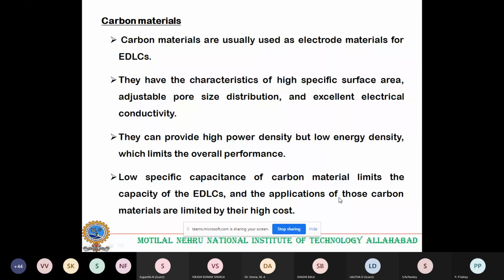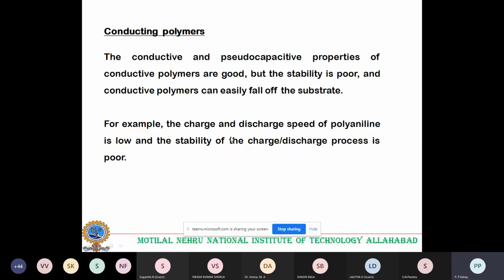Now, conducting polymers. The conductive and pseudo-capacitive properties of the conducting polymers are good. This polymer is also conducting, and pseudo-capacitive properties are also good. But the electrochemical stability is poor, and conducting polymers can easily fall off the substrate if you do a number of cycles. So the chemical stability is poor, and there is a chance that the conducting polymer may fall off from the substrate. For example, the charge and discharge speed of polyaniline is low, and the stability of the charge-discharge process is poor. So conducting polymers have their own limitation.